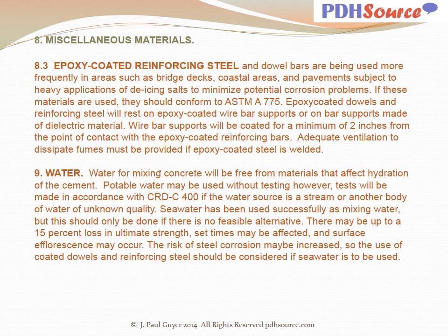However, tests will be made in accordance with the appropriate standards if the water source is a stream or another body of water of unknown quality. Seawater has been used successfully as mixing water, but this should only be done if there is no feasible alternative. There may be up to a 15% loss in ultimate strength, set times may be affected, and surface efflorescence may occur. The risk of steel corrosion may be increased, so the use of coated dowels and reinforcing steel should be considered if seawater is to be used.